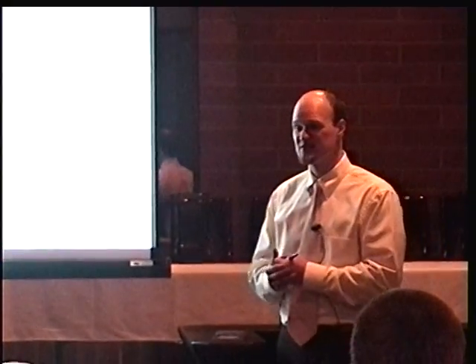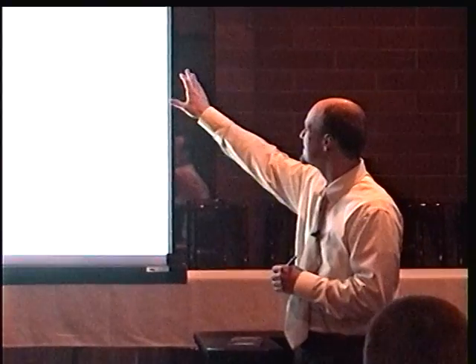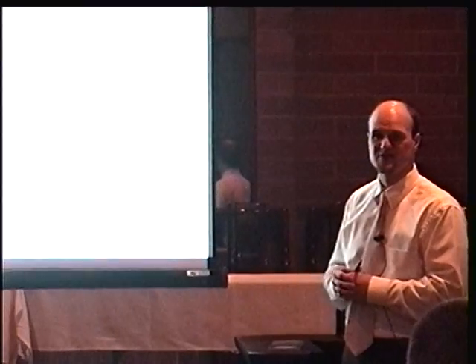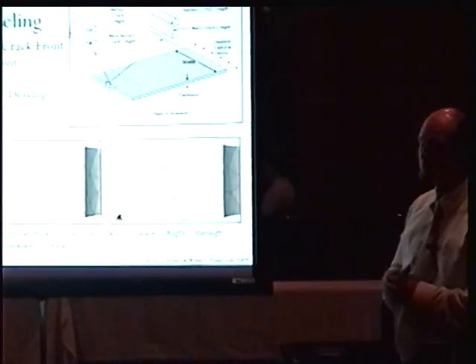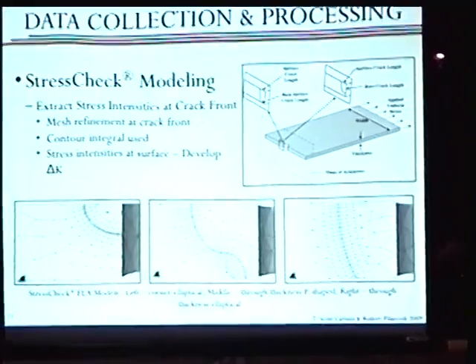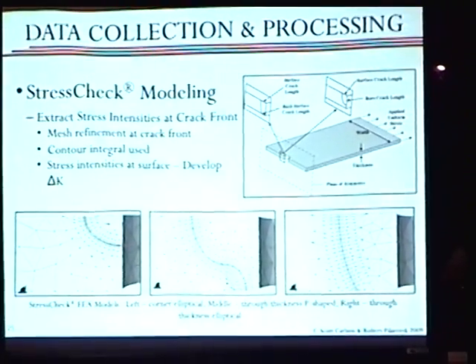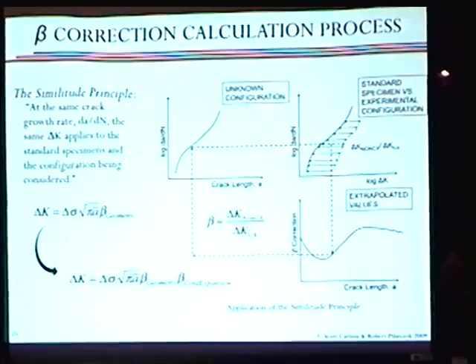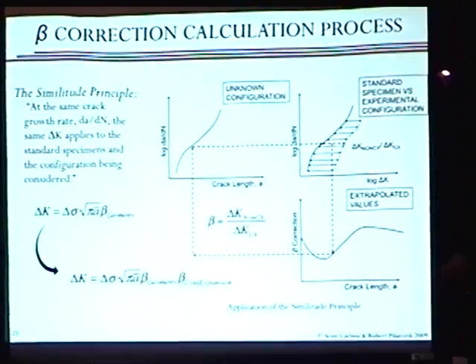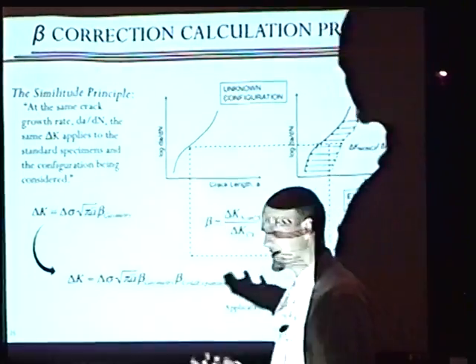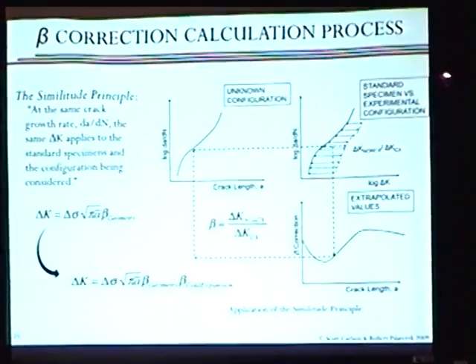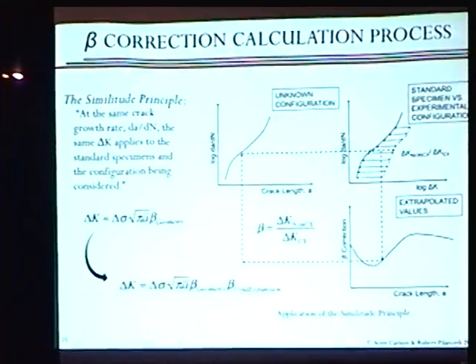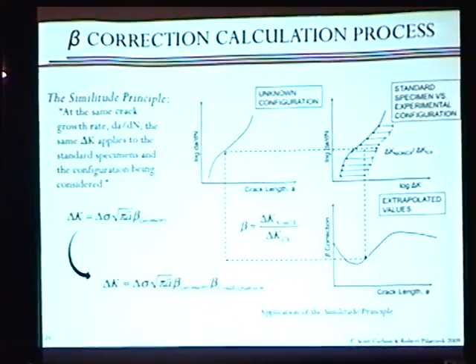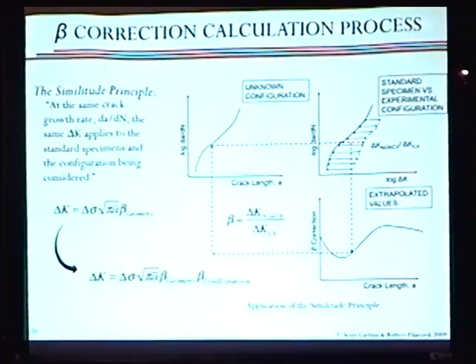So we needed to get the stress intensity. We had to put together finite element models to understand, for our given component, our given loading, and our given crack shapes, what the stress intensity was as a function of crack size. That's how we worked through to understand stress intensity versus crack size for all these different components we tested. Slide. Once we understood that, we had to come up with a beta correction. Can we capture this benefit in terms of a beta correction? It's a different way to look at it, but from a sustainment point of view, it's a great way to handle it.